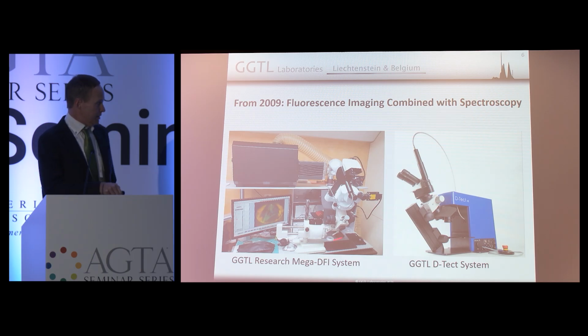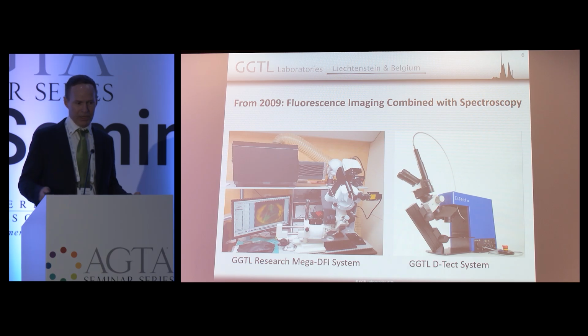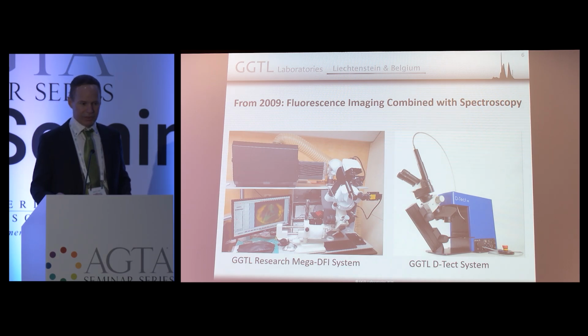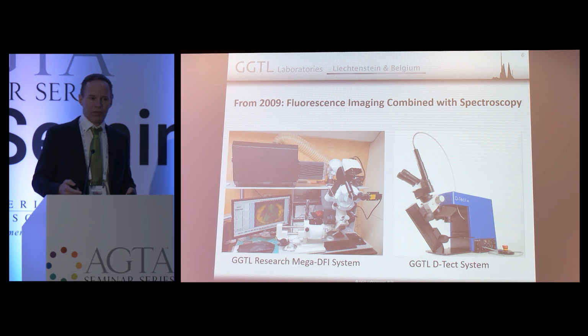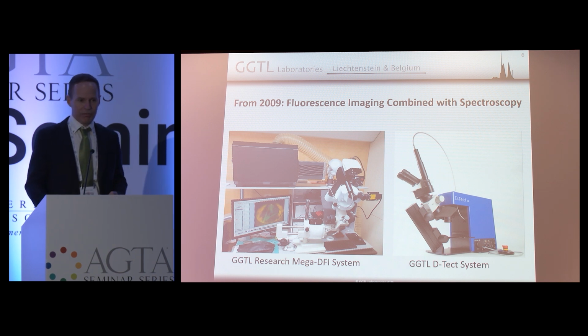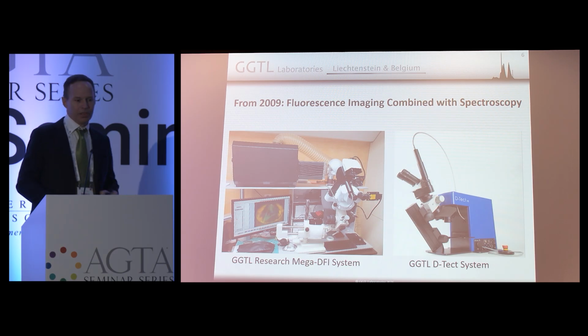This is the DFI. This is the biggest one we have. This is a very high power xenon source that has been suitably filtered to enable us to excite a diamond with any wavelength in the UV. So anywhere from 210 to 400 nanometers we can excite. And we enclosed a laser here and a laser in the back, so we can also excite at 405 and 532 nanometers for fluorescence imaging, fluorescence spectroscopy, and also Raman spectroscopy, so we can do all in one.